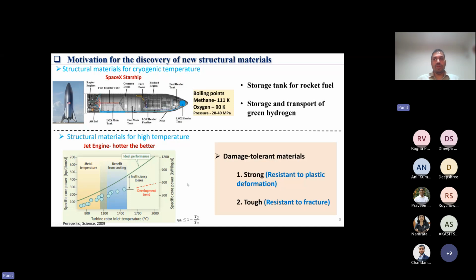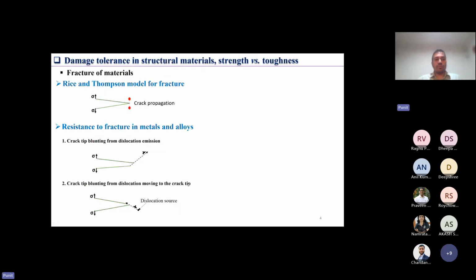These materials should be damage tolerant. And when I say damage tolerant, what does it mean? It means that materials should be strong, which means they should be resistant to plastic deformation. And these materials should also be tough, which means they should be able to resist fracture. So if we talk about how materials fracture, we can take the basic idea of the Rice and Thomson model, where they say that if you have a crack, and you apply stresses at the crack tip, and in that case you break an atomic bond ahead of the crack tip, it means that your material will fracture, or the crack will grow inside the material. So this is the basic idea of fracture.